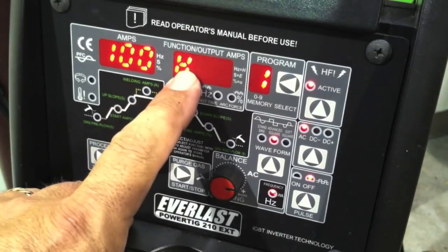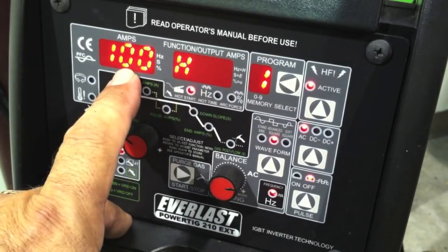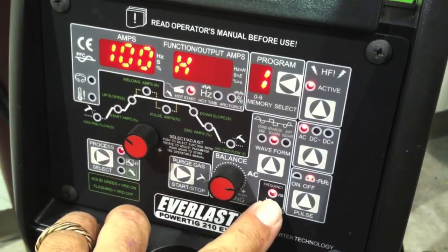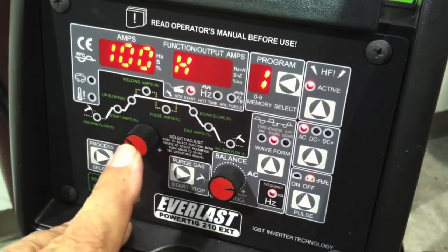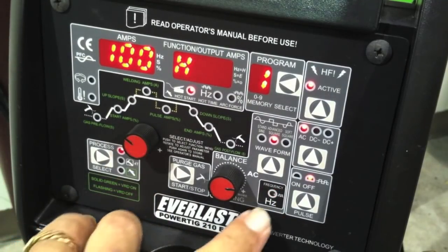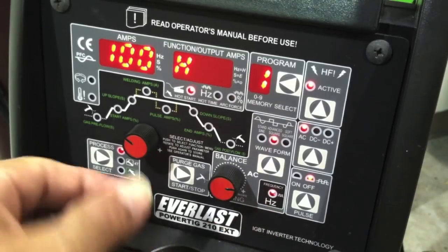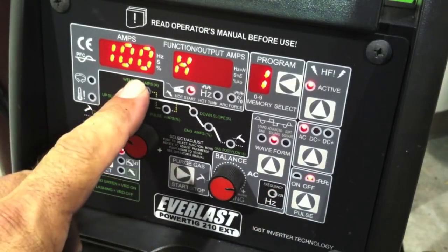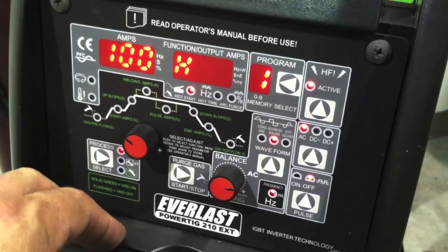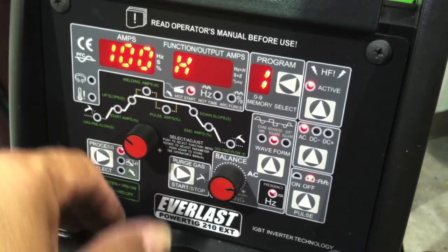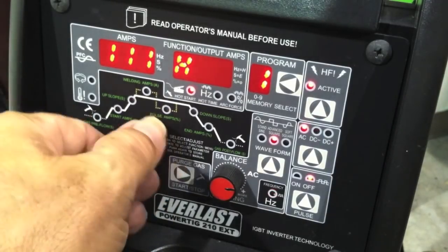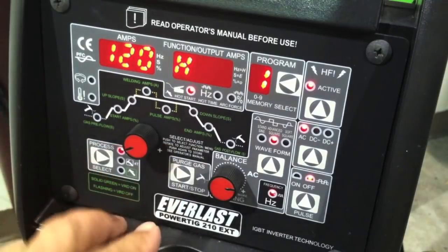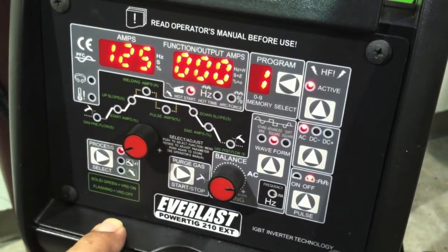And then I want to set my frequency, the frequency of the alternating current. In order to do that, I've got to get this little frequency light blinking before I can set it. So I press that, get it to blinking, and then anywhere between 100 and 120 is a good setting for frequency for all around work. I kind of want to focus the arc a little bit because I'm using a sharpened electrode. And so I'm going to set it on up to 120 and then lock that in there. And I'm pretty much ready to go. Off to the races.